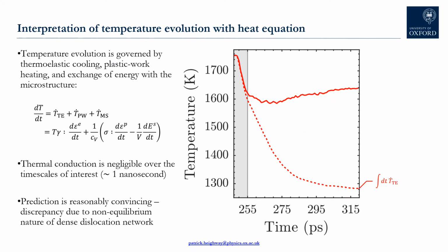In principle there are 3 source terms. There's the thermoelastic cooling term, T.Te, which depends on the Grüneisen parameter gamma and the elastic strain rate d epsilon E by dt. There is the plastic work heating term, T.Pw, which depends on the Cauchy stress sigma, the plastic strain rate d epsilon P by dt, and the element's volumetric heat capacity Cv. And then there is the rate of change of energy stored by the microstructure, which is labelled E superscript S. Note that thermal conduction is completely negligible over the timescales of interest here, i.e. nanoseconds, hence there being no diffusive term in the heat equation.